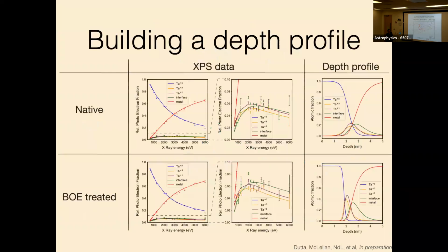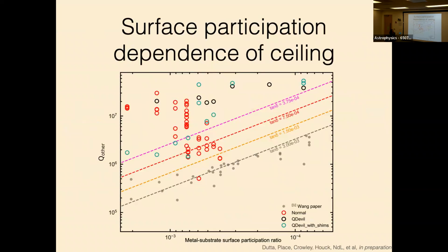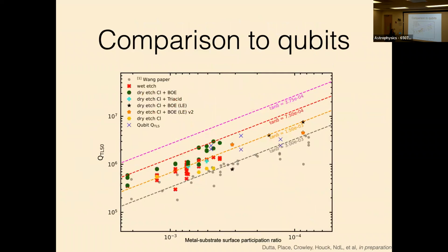Let me just skip this XPS story. The other thing that we can do is look at this ceiling that sets the top of all of these plots, and we can look at whether or not there's any surface participation dependence of that, and we see that it's basically flat. And we also use this as a way to diagnose a lot of what was ailing us in terms of packaging and coupling to free space modes. So this parametrization is really powerful for being able to figure out whether or not you're measuring the right thing.